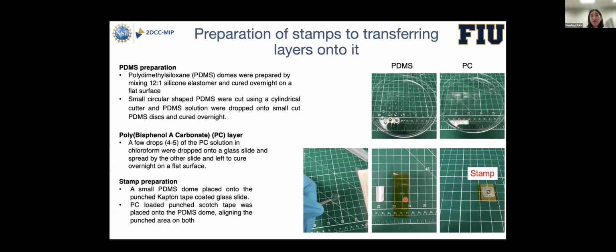In order to do that, we had to prepare the stamps, which are basically made using two different polymers. First, we needed to make PDMS domes, which is polydimethylsiloxane. And how do we prepare these domes? We take a mixture of 12:1 silicone elastomer, mix them thoroughly, and then keep it overnight to cure. And then the next morning, we used a cylindrical cutter to make small cylindrical cuts into it.